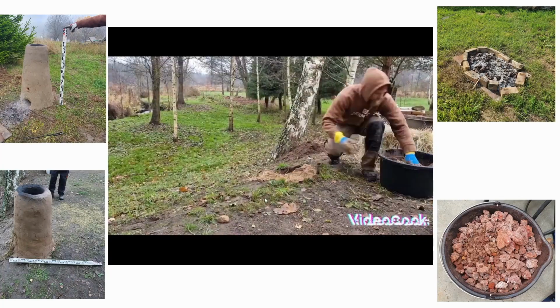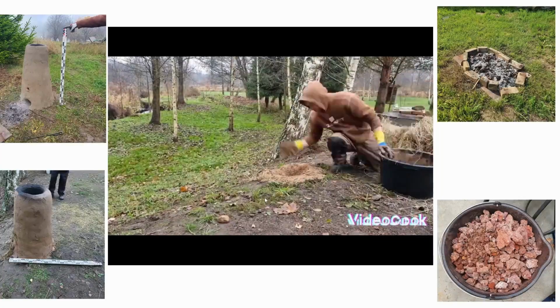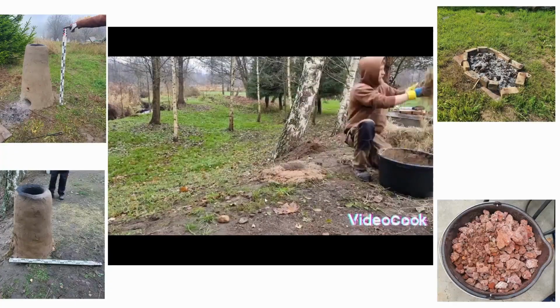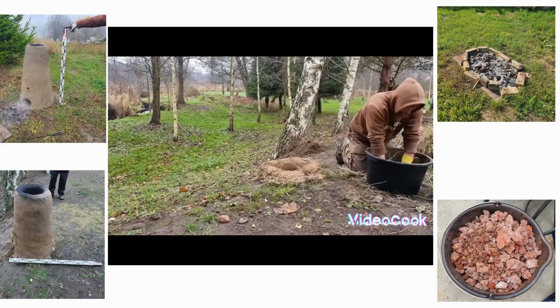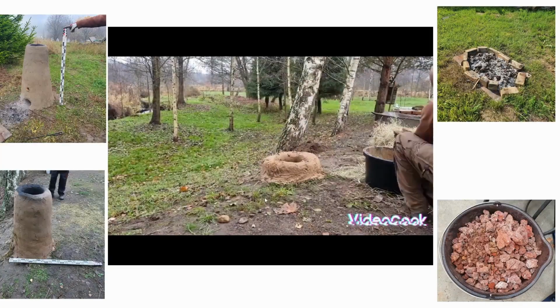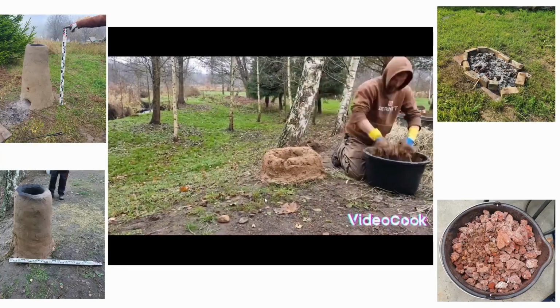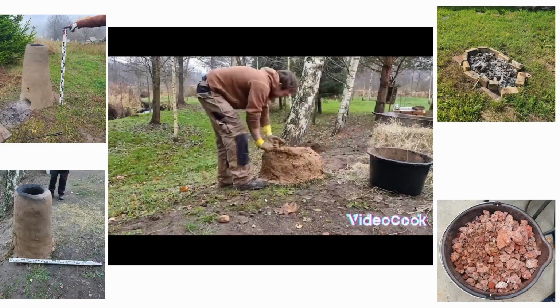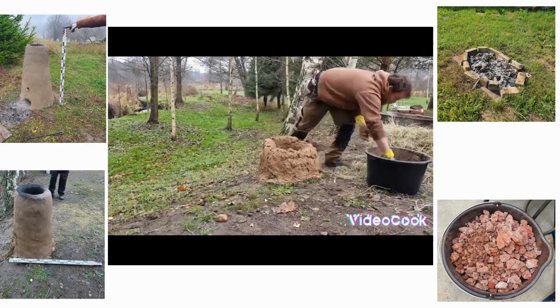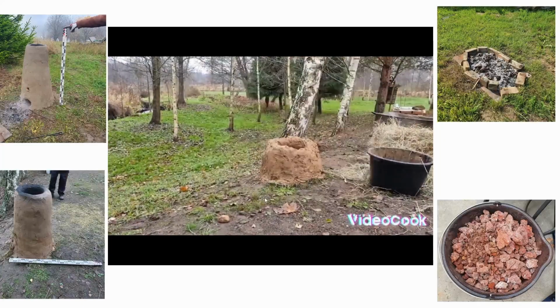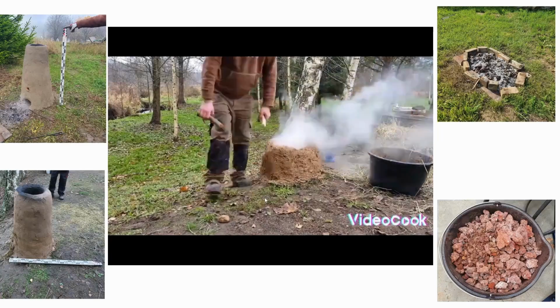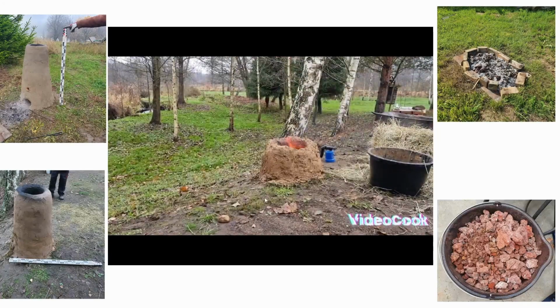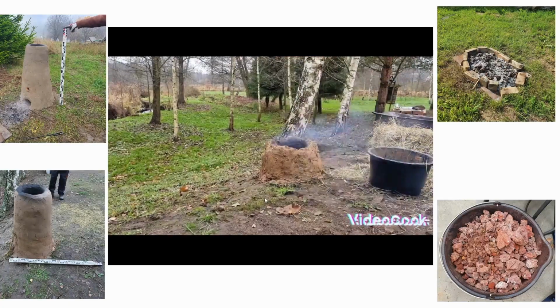The furnace sizes were determined based on archaeological data. We used two types of furnaces, one with a slag pit below the shaft and another with a discharge hole, similar to what is shown in this video. With prepared materials, an experienced operator could set it up in about 4 hours. Before smelting, the ore was roasted to slightly enhance its iron content. And for our initial experiments, we used coarse ore that had been only lightly crushed.